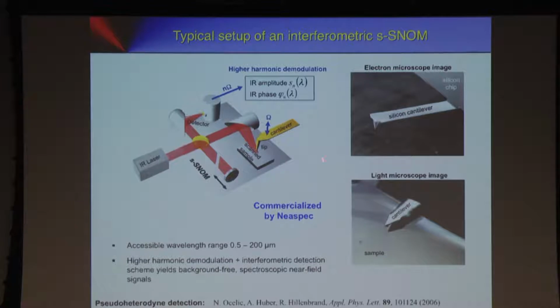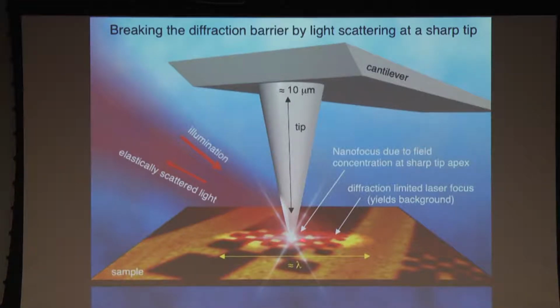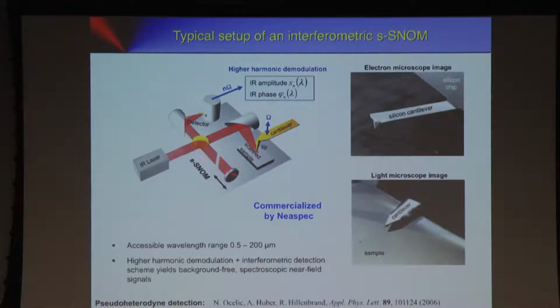Now, another trick, or the major trick, is that we demodulate this detector signal here at a higher harmonic of this modulation frequency. And to explain that would take too much time. You should just believe me that this higher harmonic demodulation is actually the trick to extract the information that comes from this tiny little nanofocus here out of this background. In the end, it's the combination of this interferometric detection together with this so-called higher harmonic demodulation technique that gives us access to the nanofocused light here at the tip apex.